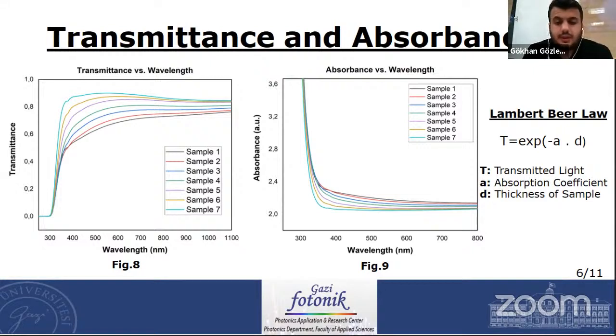As can be seen in figure 9, the absorption edge shifts towards longer wavelength with increasing film thickness. It indicates a blue shift in thinner films compared to bulk titanium dioxide. This situation is related to the quantum confinement effect.